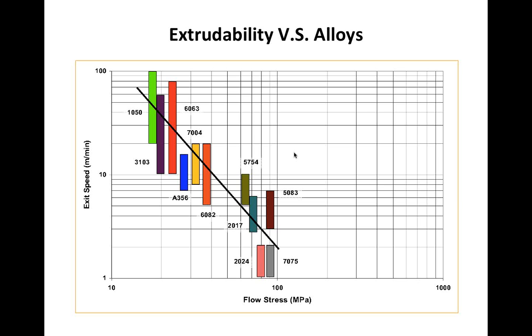And if you look at the other end, the green one, you have 1050, the 1000 series alloys. The flow stress of that is almost 10 times or 5 times smaller than the 7000 series alloys. So that's why it's very easy to extrude, and extrudability is higher on that end. So this graph shows you the trend from soft alloy 1000 to hard alloy 7000 series, and their flow stress and extrudability relationships. You're better at that than I am.